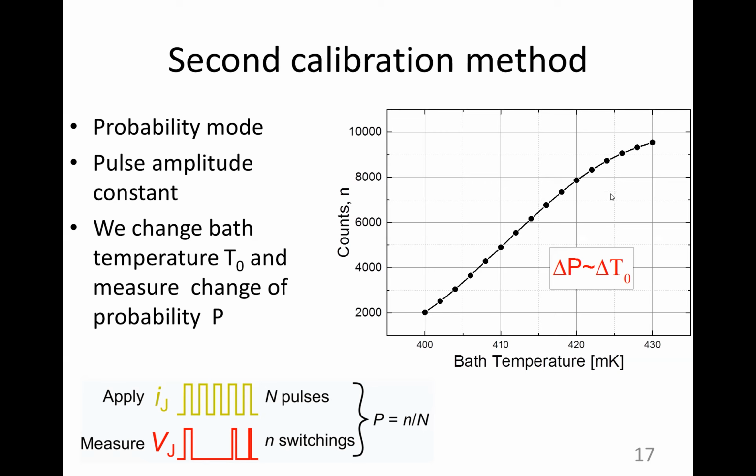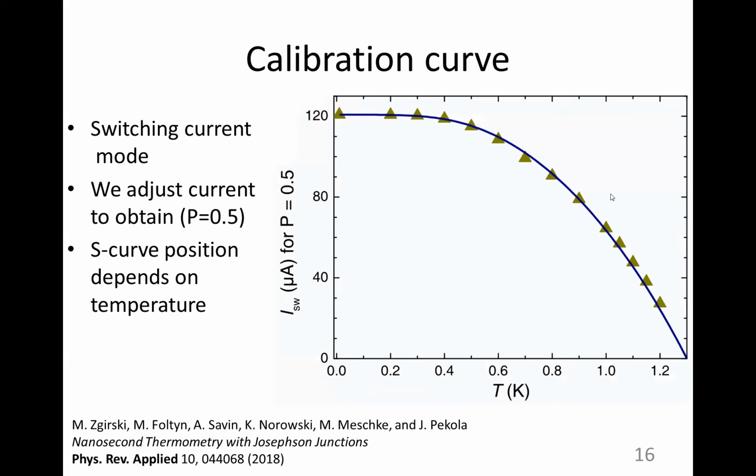So the range of the sensitivity here is of the order of tens of millikelvins, whereas here we can trace the temperature gradients from Tc basically to 0.4 K, where our thermometer usually stops being sensitive to further changes in temperature.